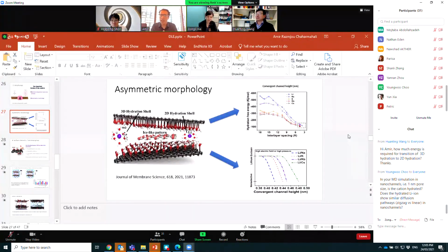The other things are the binding energy, the trapping energy, and the entrance barrier energy. All of those also have to be considered when it comes to the separation of ions. Most of the literature focuses only on the hydration energy, overlooking the contribution of other energies. The other one is, for example, the energy of the ice-like patterns inside the nanochannel when it goes below 1 nanometer, and how we alter this energy when it comes to the interaction of the ions with this ice-like pattern. All of those energies are important in this transport phenomenon. If you look at all the energy, there are different factors.